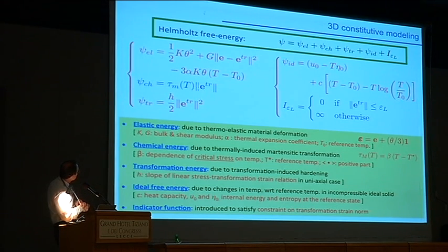Besides the linearity in the norm of the internal variable, there is this other factor, τ_M, which is chosen in this form down here. You probably don't see the Macaulay bracket very well. This is basically the positive part function. So τ_M is a piecewise linear function of temperature: when T is below T*, this term is 0. When T is greater than T*, this term varies linearly with T, and the dependency on temperature above T* depends on the material parameter β. So here there are two very important ingredients, material parameters, which are T* and β. The other interesting term is this quantity here, which is the indicator function, which can be seen as a mathematical tool to take care, in a sense automatically, of the constraint on the transformation strain norm.